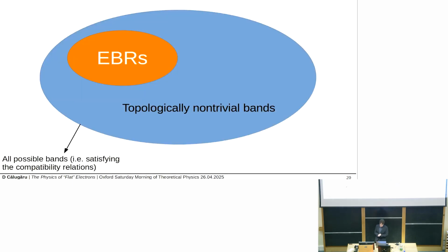So let me visualize that. This diagram shows the landscape of all possible band structures that are allowed by symmetry. That is, all bands that satisfy the compatibility relations in momentum space. Within this full space, we have a distinguished small subset, the elementary band representations. These are band structures that arise from symmetric localized orbitals in real space. In other words, atomic limits. And here's the punchline: not all symmetry-allowed bands come from a localized real space description. By definition, such bands are topologically non-trivial. And this diagram captures the logic of topological quantum chemistry.